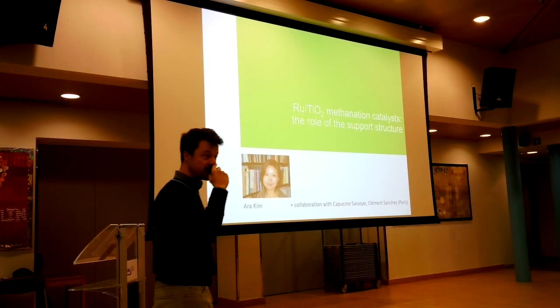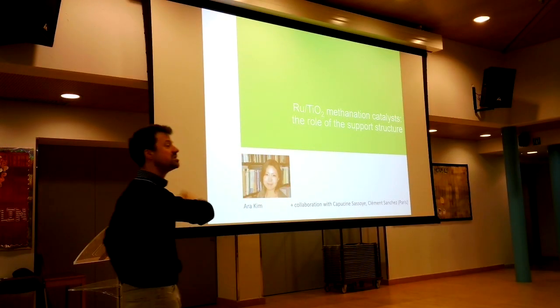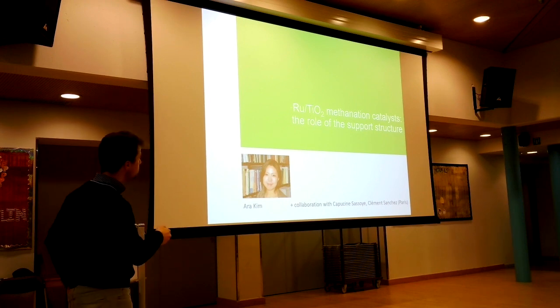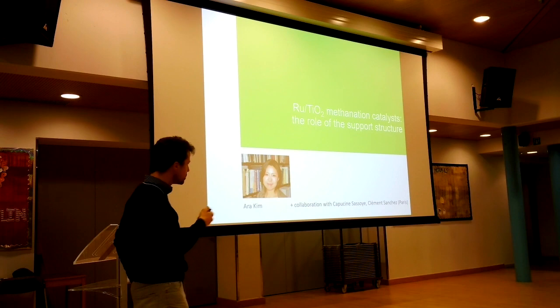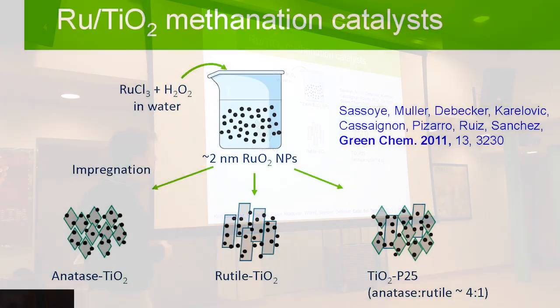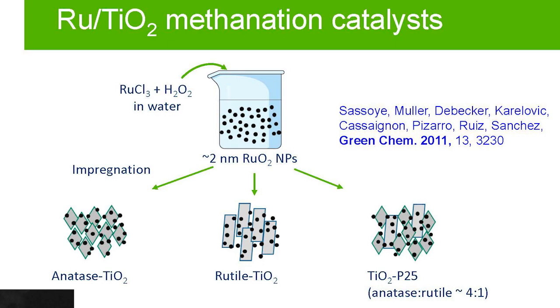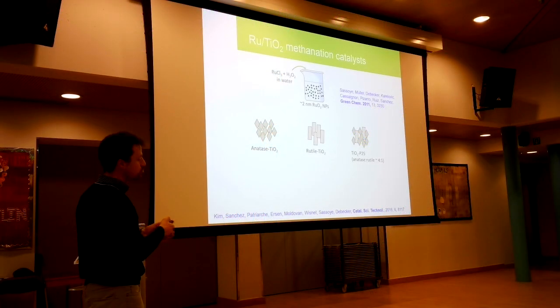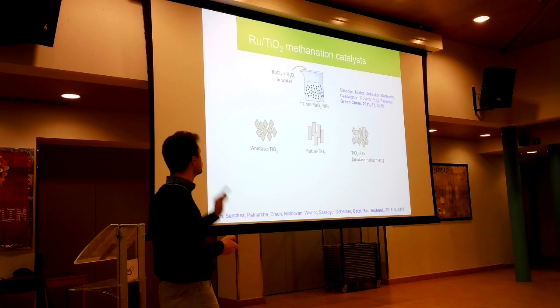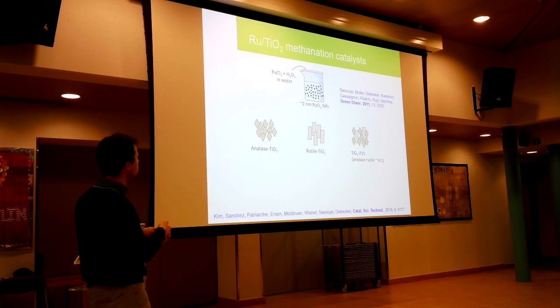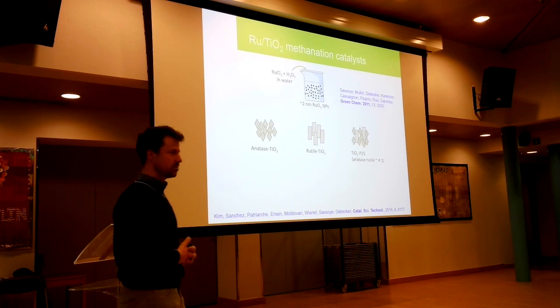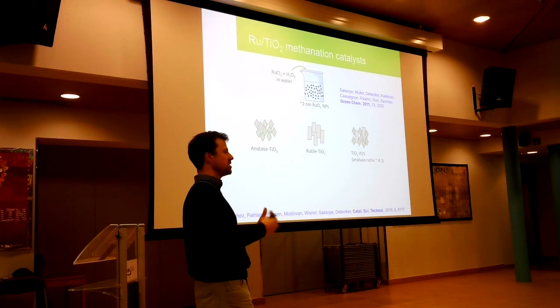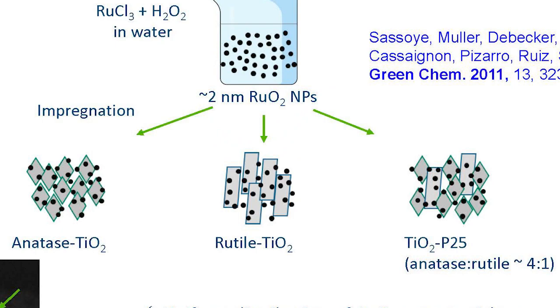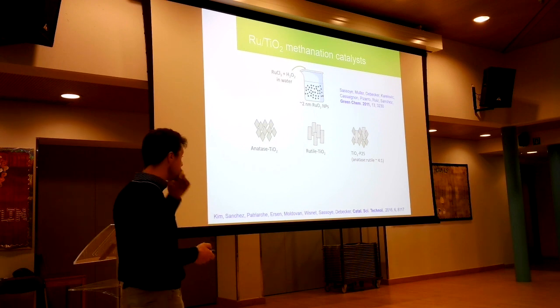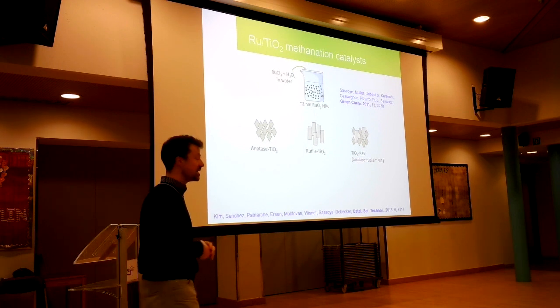We know that ruthenium is a very good catalyst, so Sabatier was studying nickel, but ruthenium is even better, right? But you have to disperse this ruthenium onto a support, in this case titania, and we wanted to study those interactions. So we started with a system that was kind of interesting. We thought it's a possibility to prepare a suspension of colloids, or nanoparticles of ruthenia nanoparticles, 2 nanometers, and then a series of different titania supports. You know that titania can be crystallized in different structures. So you have anatase, you have rutile, and you have a commercial support that is very famous in the field. It's called P25, and it's a mixture of anatase and rutile.